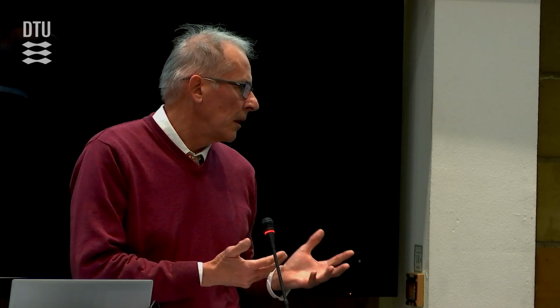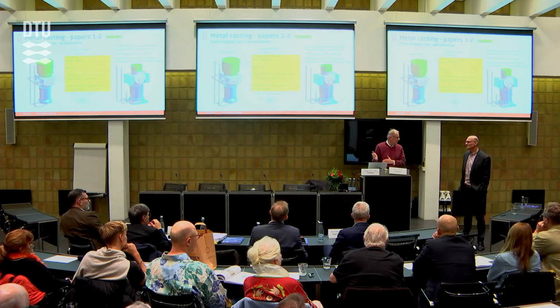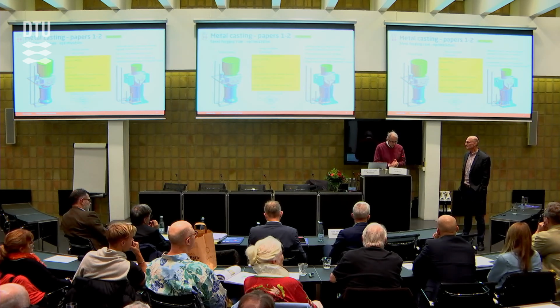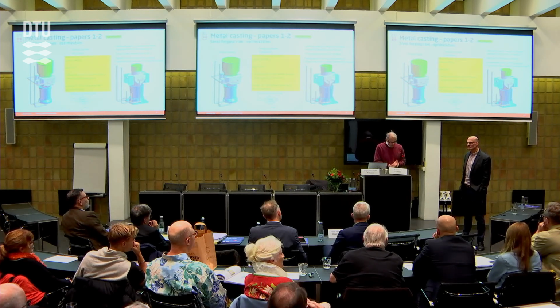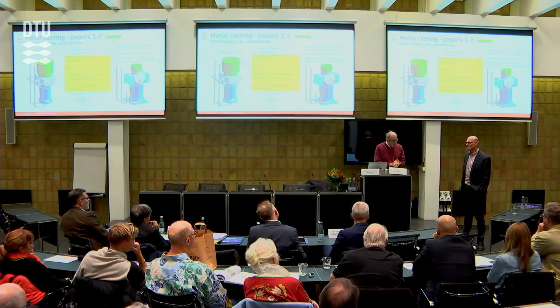Exactly. Okay. And that was really verified, let's say, and you have perfectly illustrated that when you passed the specimen into the synchrotron. It was really a nice study. So, what was really the first order factor? It was to take into account the residual stress, or to take into account this peripheric region in the nodules?